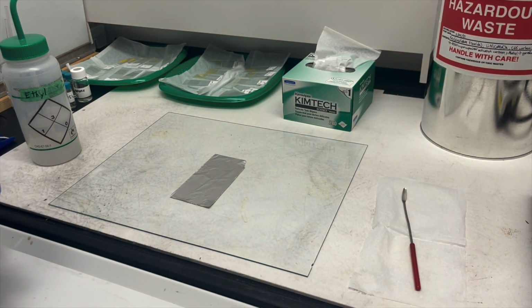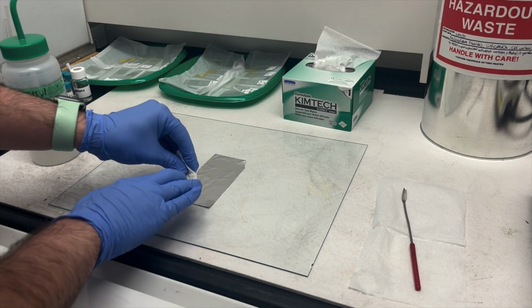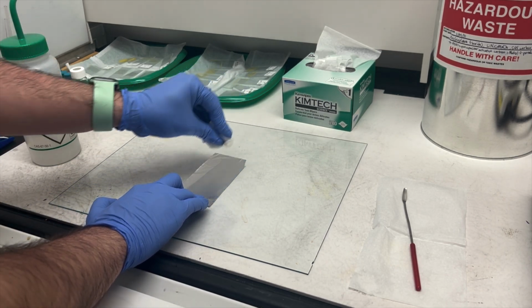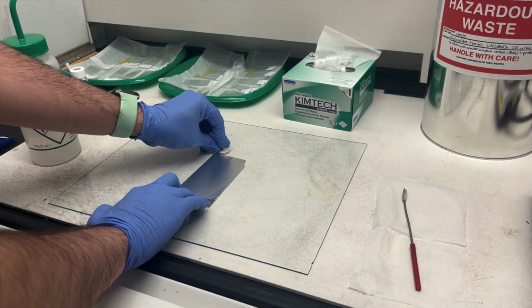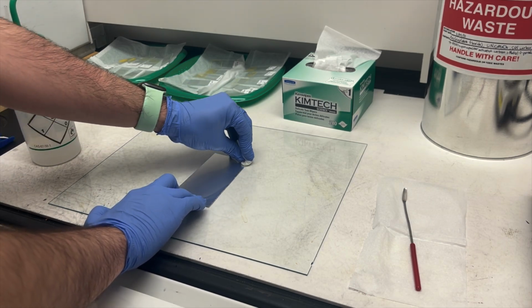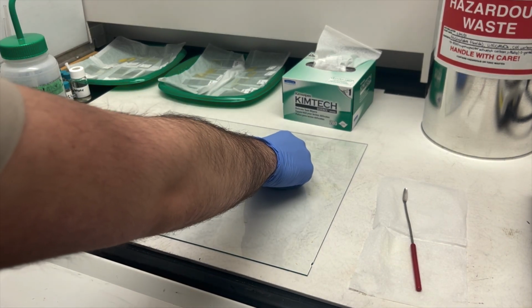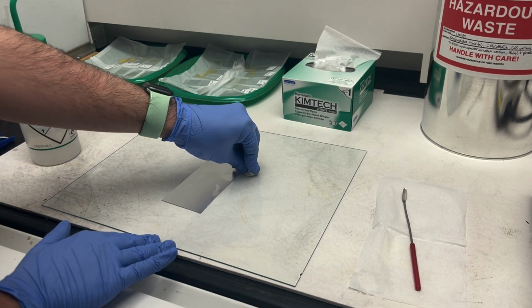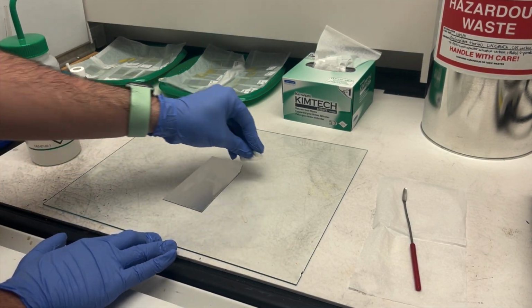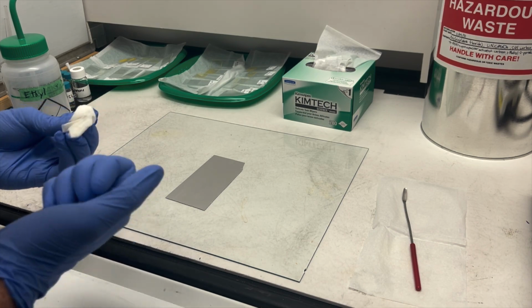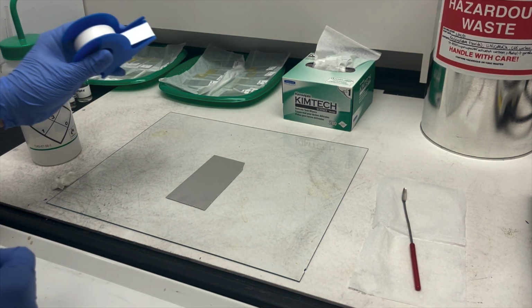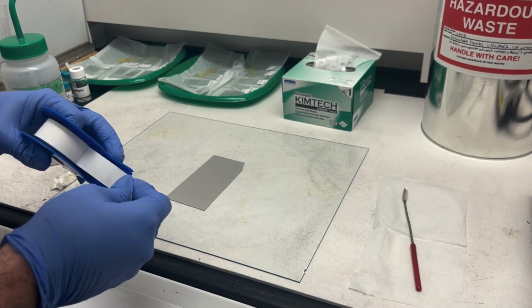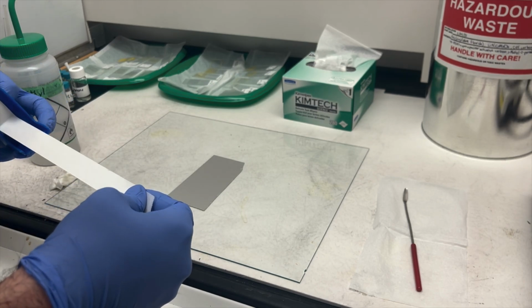Having the ethanol underneath the foil allows it to almost stick. With another Kim wipe, we can smooth out the foil, which we do so that the slurry is deposited evenly over the entire surface. Now I'm wiping off the excess ethanol on either side of the foil so that I can place tape down, creating a thin strip to deposit the slurry.